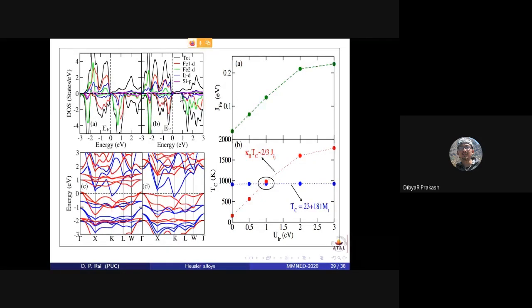But when we apply the U value, we give the U value for these Fe elements. When you apply the Coulomb repulsion term to each of these iron elements, then we got different results. We found the band gap out here, and from the band structures also we found the band gap in the spin down channel. So we claim this Fe2IrSi is a half metal ferromagnet compound.